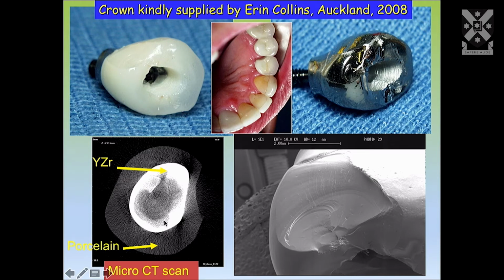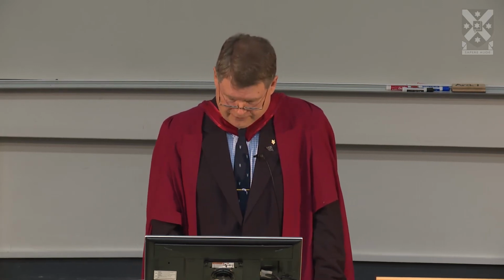We also did a micro CT scan on it. And this here shows you the surface. And using fractography, which is a science in itself, we can track back from the different areas to the source of the failure, and we're even able to calculate the forces involved in initiating that failure.